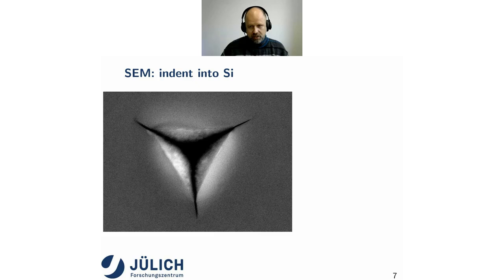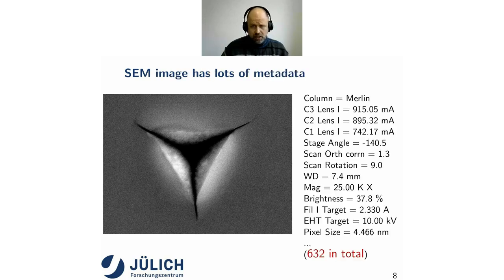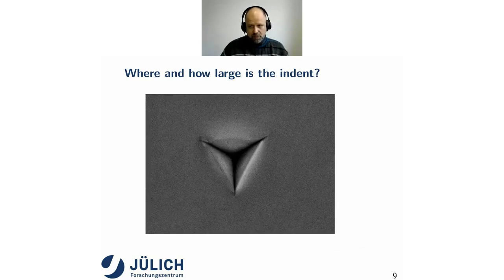If we look at an indent in the SEM, this is how it looks on silicon. You clearly see that in this case the silicon has even broken a little bit, but you kind of see the imprint. If we now look at the image that we get in this case from a Zeiss microscope, you can see that we get lots of metadata which we then can use to precisely determine the length scale, which is definitely needed. So how large is the indent in this case? This image recognition is very popular. Even if you drive your car to work in the morning, you might use image recognition to tell you the speed sign on your way to work.